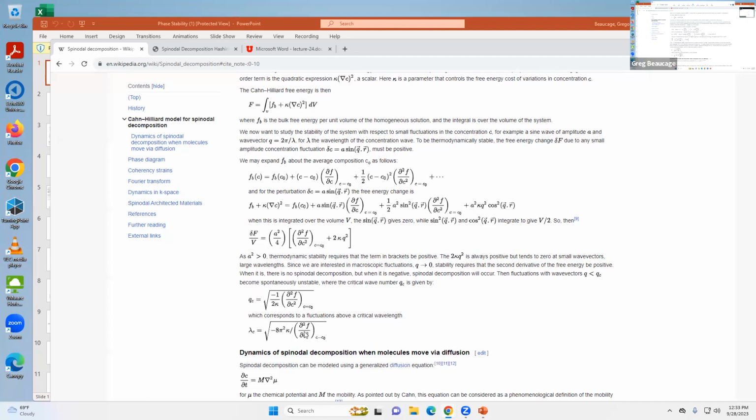So this thing has to be negative, meaning it's a frown, meaning it's phase separating. So you're into the spinodal region to get this critical size. If you have size larger than that, it phase separates. If it's smaller than that, it dissolves. That's the point of this first part. But the main thing of the spinodal is you're going to get a fixed size. You have a happy size where it decides to grow for given transport properties and a given thermodynamic driving force. This doesn't give that to you.